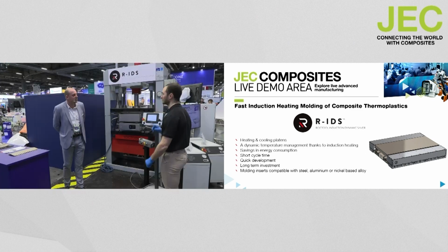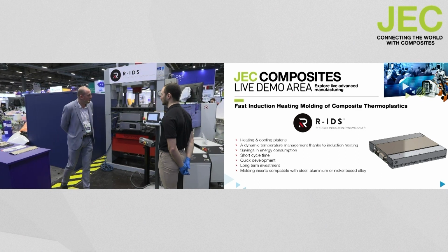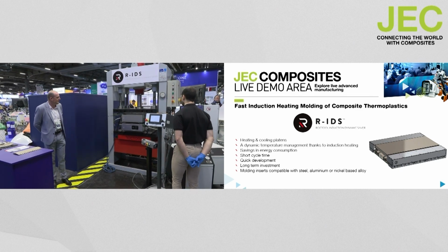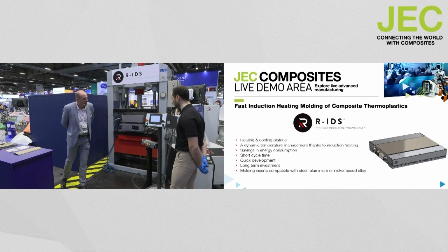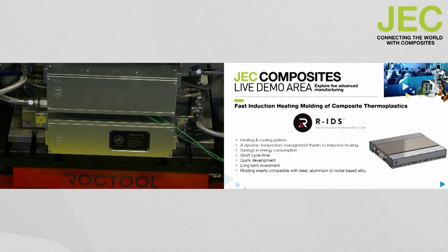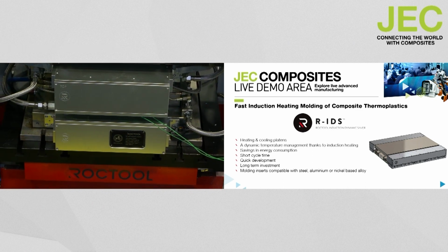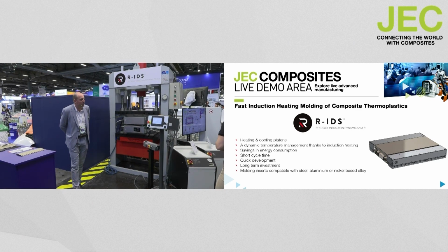So now, as we reach this temperature, we have reached 240 degrees on the top of the molding surface. And you have here the information about the thermocouple integrated in the heat platen. As we reach the maximum temperature, we can stay at the same temperature for the holding time. In this configuration, we just stay a few seconds, and as we reach this temperature, we start to cool down.